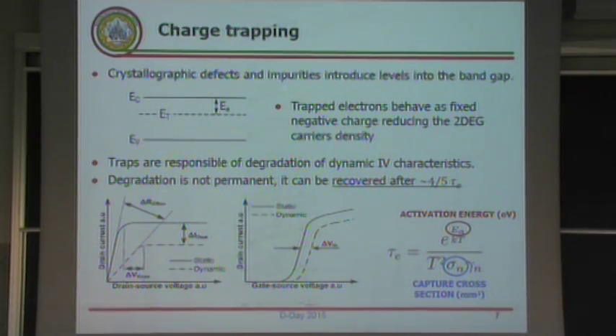And the problem is that during device operation, because of the high electric field, electrons can be injected into this trap state. Once the electrons are there, they are frozen or trapped because they have zero mobility and cannot participate in the conduction. They behave like a fixed negative charge, and the result is that they reduce the amount of charge available for the conduction in the two-dimensional electron gas of the device.